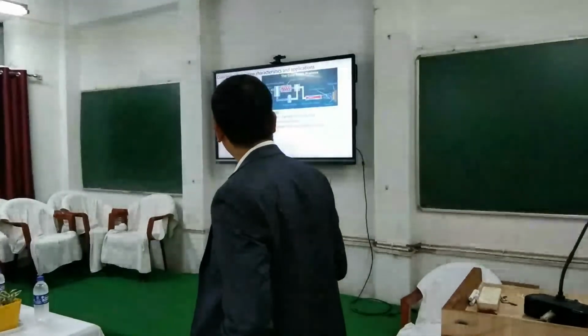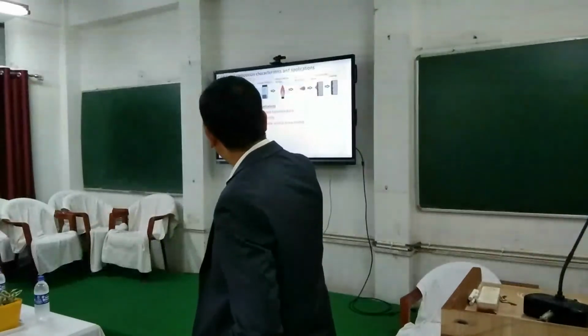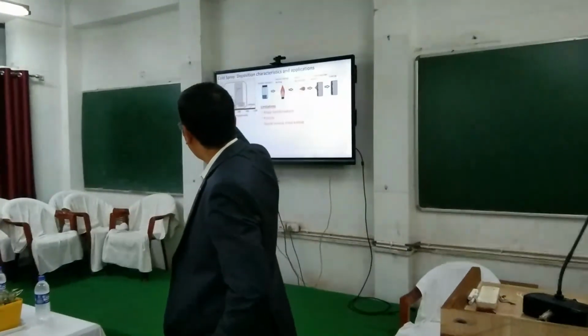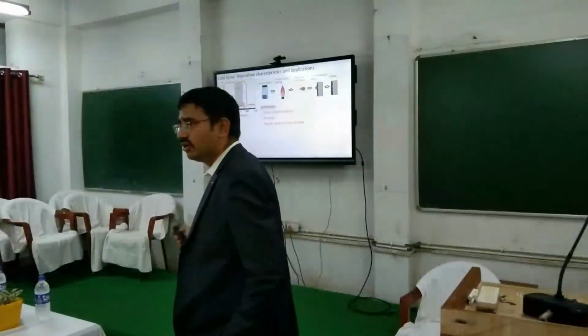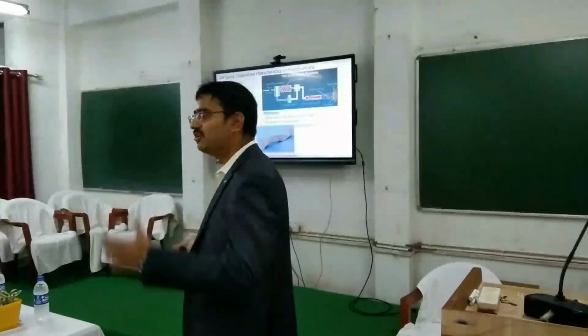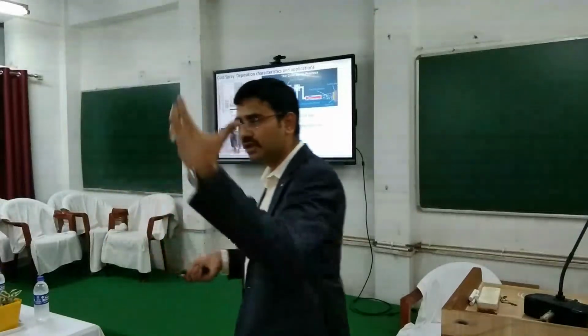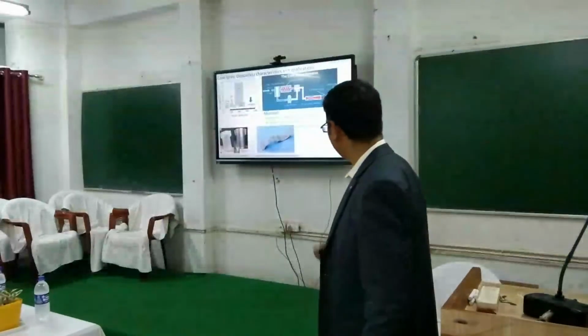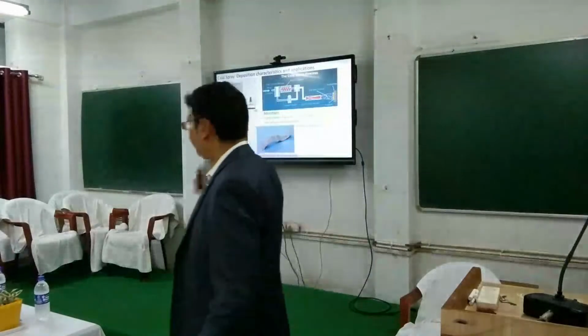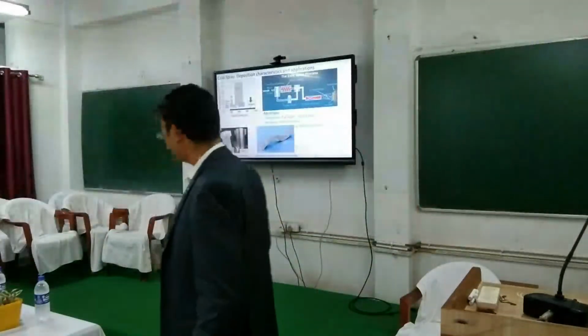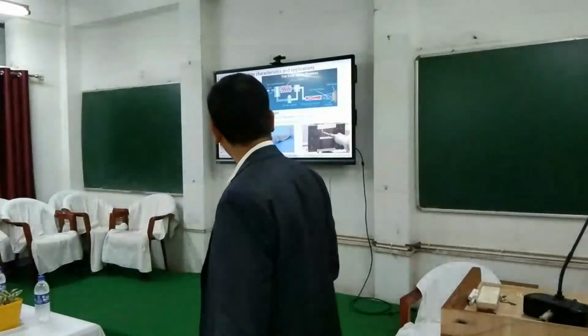So, cold spray of titanium and titanium-based composites. If you can see the graph, the other coating processes, the plasma spray etc., are higher temperatures, whereas cold spray is a low temperature and high velocity process. So that's why it is typically used for repair of worn components, because you are preserving the bulk property of the material. It is also used to additively fabricate free-form parts. If you want to additively manufacture small free-form parts, you can actually fabricate them using cold spray. And also coatings on heat-sensitive materials.